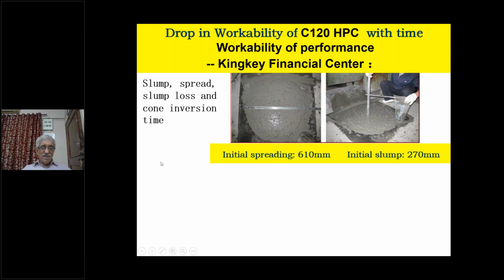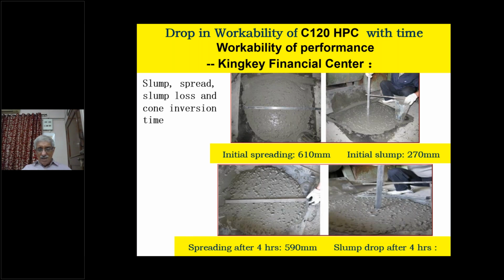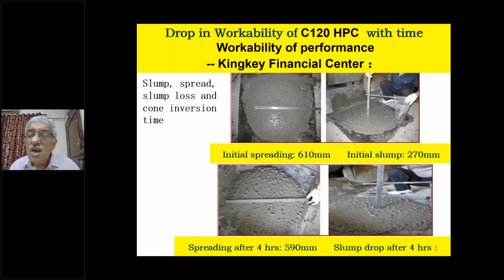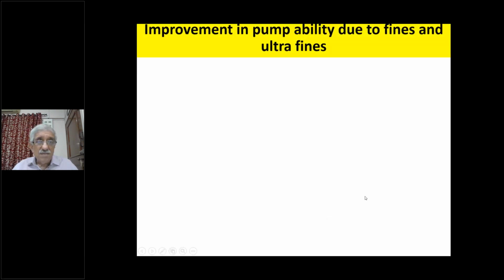This is one example from the Kingkey Financial Center, where they produced C120 high performance concrete. The initial spread was 610 and the slump was 270 millimeters. After 4 hours, the retention was 590 millimeters of spread, and the slump dropped to about 40 millimeters. Improvement in pumpability is due to fine and ultra fine material.